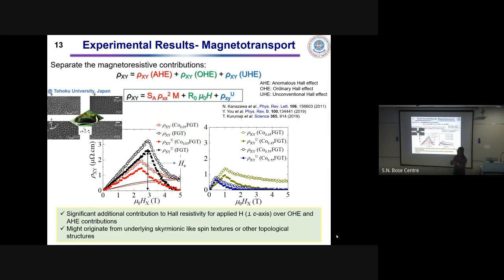That's why, and also because of that, the size that we got is around 600 nanometers. That's quite large compared to the known magnetic Skyrmion size. So that's why we are calling it Skyrmion lattice kind of patterns, but with the measurement resolution that we had, we could not separate out the domain and the Skyrmion textures.